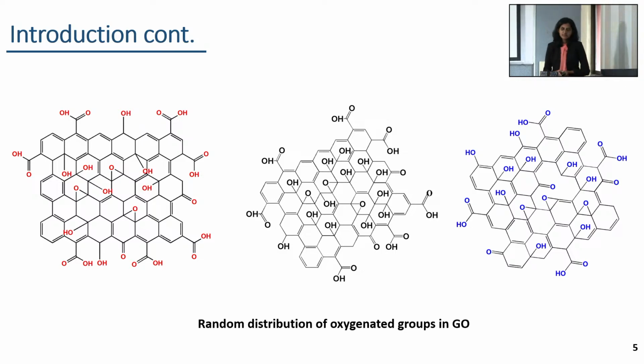So, basically the structure of graphene oxide is highly dependent on the type of graphite, the type of oxidant as well as the oxidation parameters such as oxidation temperature and oxidation time. Therefore, controlling these oxygen functionalities during the graphite oxidation into graphene oxide as well as the reduction into reduced graphene oxide is highly important to realize their potential for real applications.